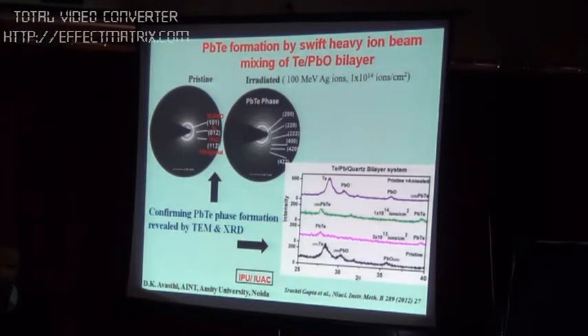I'll show you two cases here. Lead telluride is a well-known thermoelectric material, and we tried to make it. We deposited tellurium on lead, two layers, with a thermal evaporator here. One can deposit these two things. But the thing is, when we deposit lead, it is always oxidized. Whatever vacuum you have, there is enough oxygen to oxidize it, and you get lead oxide.